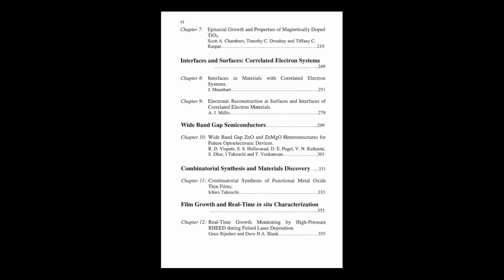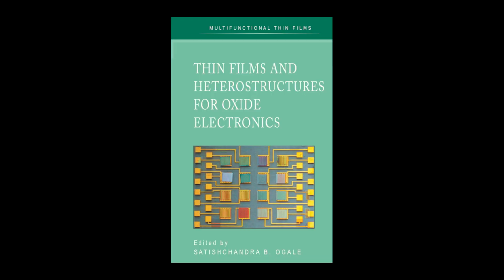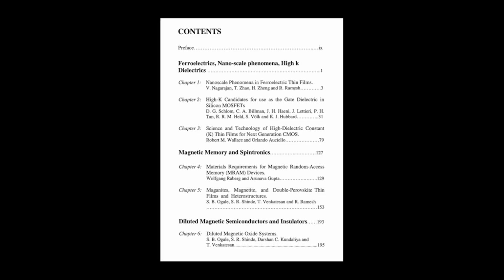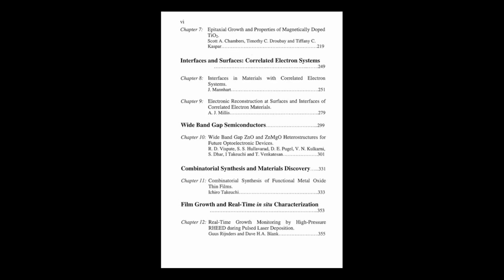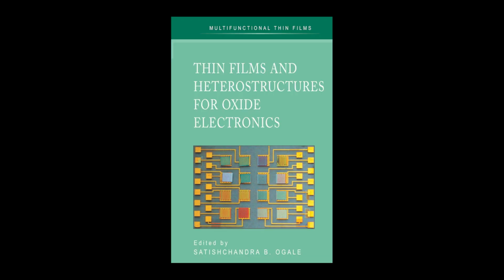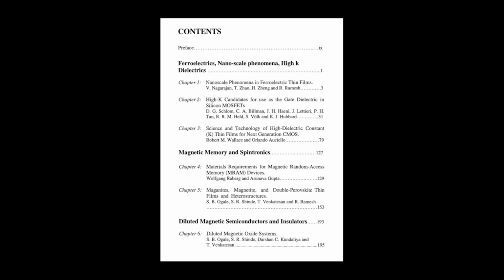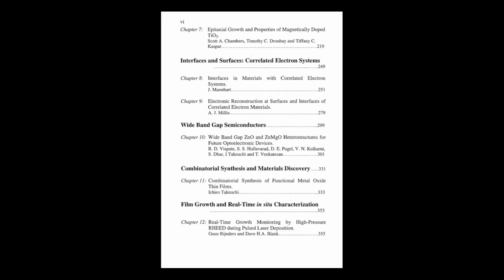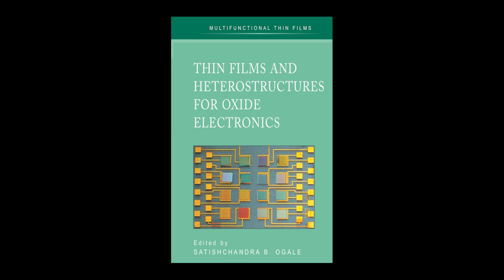People must have been looking for a definitive test, a smoking gun for intrinsic FM. They were, and for a while many thought the anomalous Hall effect, AHE, was it. Anomalous Hall effect. How is that different from the normal Hall effect? The normal Hall effect just depends on the magnetic field you apply externally. AHE is an extra Hall voltage that depends on the material's own internal magnetization. It's considered a hallmark of ferromagnetism arising from the spin-polarized carriers interacting with the lattice. So if you saw AHE, you thought, aha, intrinsic ferromagnetism. That was the thinking. Initially, AHE was hard to spot because the samples were often too insulating. But then some groups managed to make more conductive Co-doped TiO2 films, often by controlling those oxygen vacancies, and they clearly measured an AHE signal. For a time, many in the field felt, okay, debate over. It must be intrinsic. Did the story get complicated again?